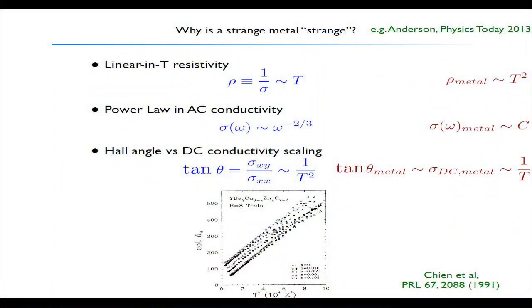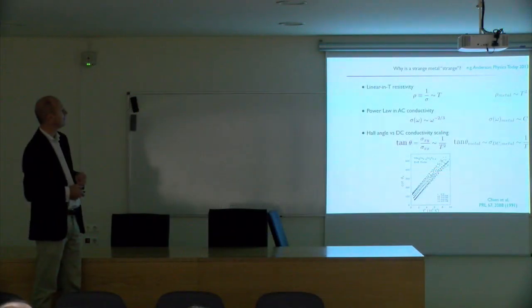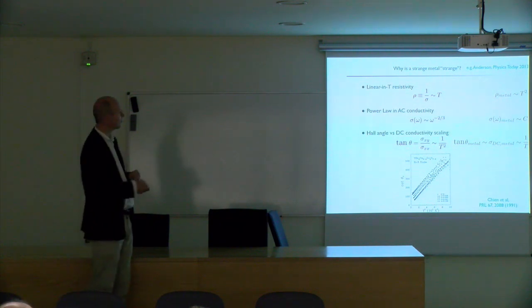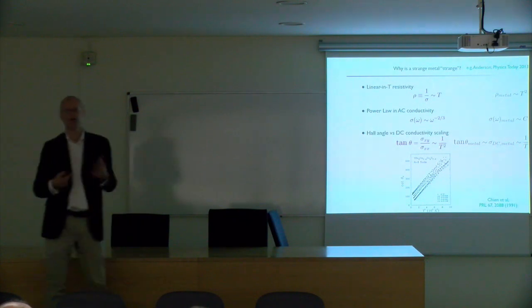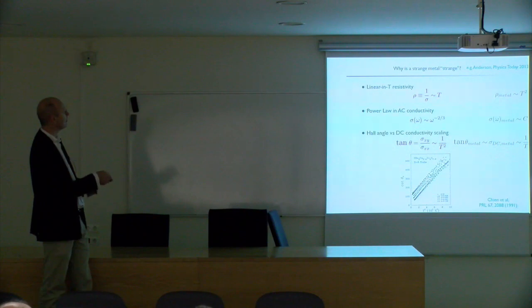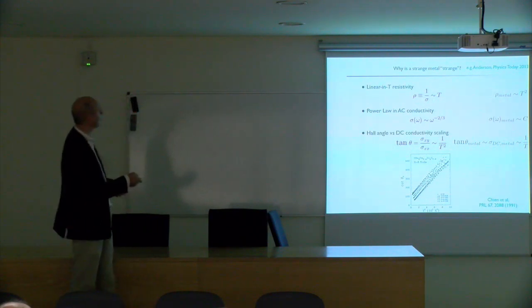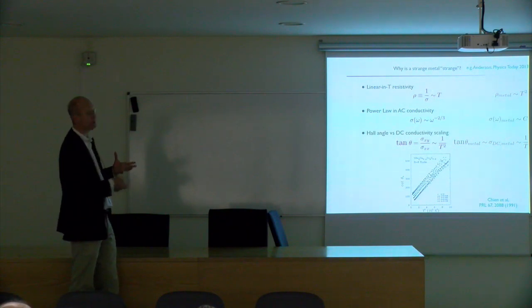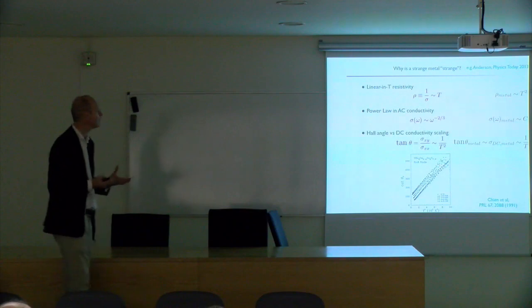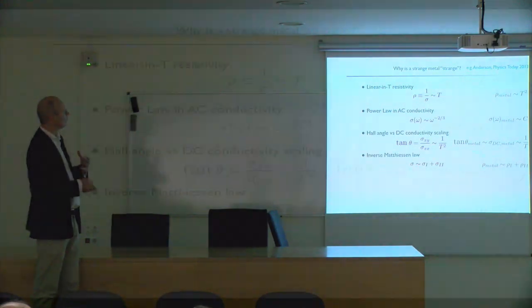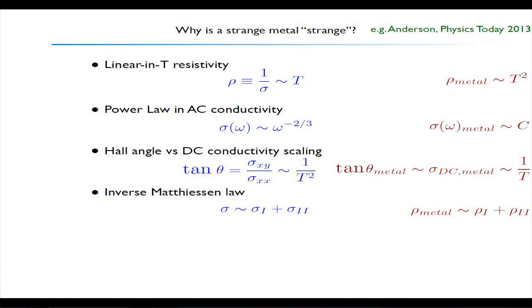A third puzzle is what's called the Hall angle versus the DC conductivity scaling. If you look at the Hall response, the Hall conductivity in the system, and you divide it by the longitudinal conductivity, just the resistivity measured in the same direction as the electric field you apply, you find that this scales as 1 over T squared. Now that is puzzling, and I will explain a little bit more later, because in ordinary metallic systems, you can show that the underlying physics that sets this scale and the ordinary DC conductivity should be the same scale. So if you know that this scales, in an ordinary metal, as T squared, then this should scale as T squared, but if this scales as T, then you expect that this also should scale as T, because it's set by the same physics. So something puzzling is going on. And now, one of the ways to explain this, and there are other experiments that show this, is that really what happens is that this mechanism must be in some way or another different.